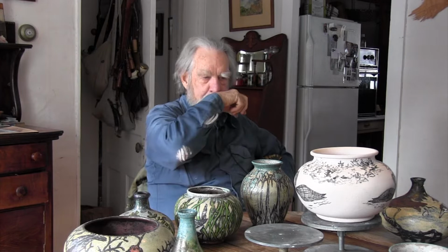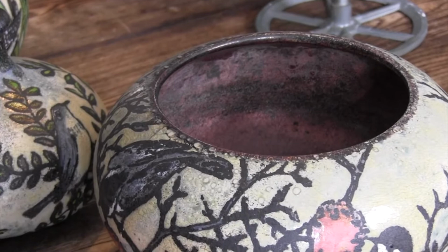And you got to go back for more, and you just touch it, and you're out. And it can be consuming at times. But you've got to watch that you don't get too much glaze on an area, or it will just bubble up. I did get a little bit too much on this lip here, and the bubbles are still there because it started to burn in various areas when it didn't have enough glaze, and these areas weren't flowing out.